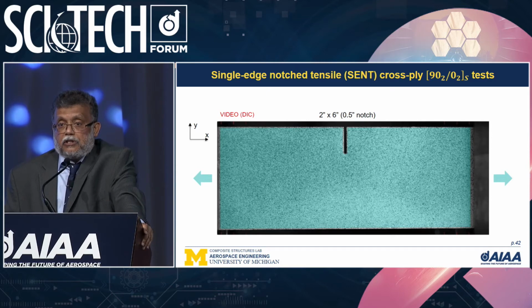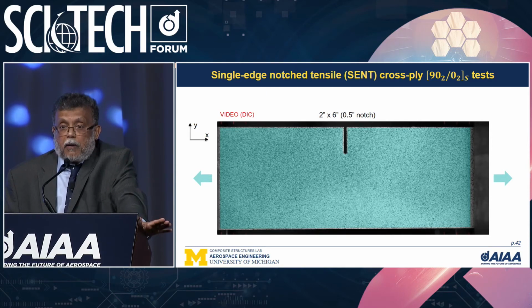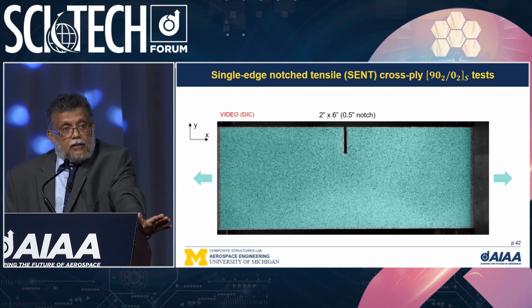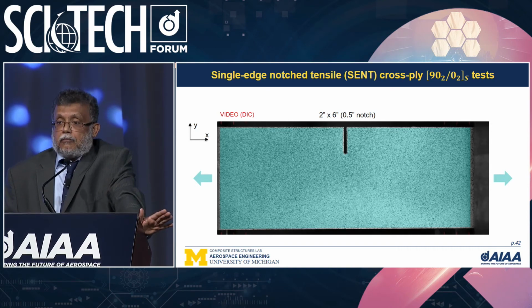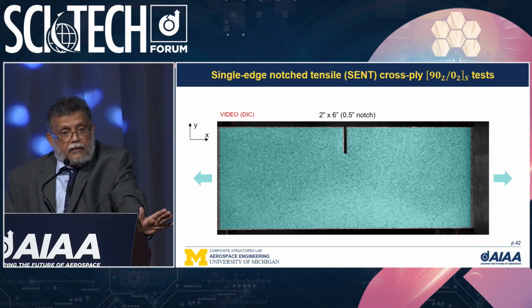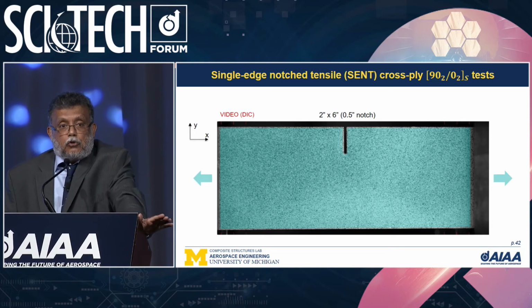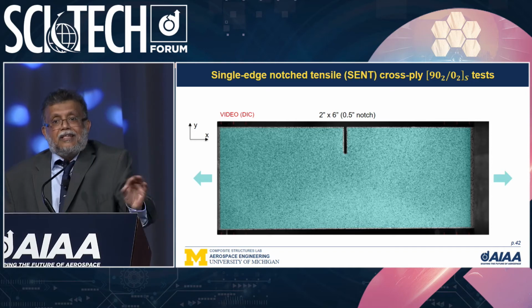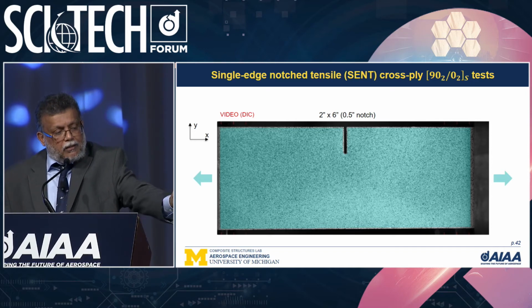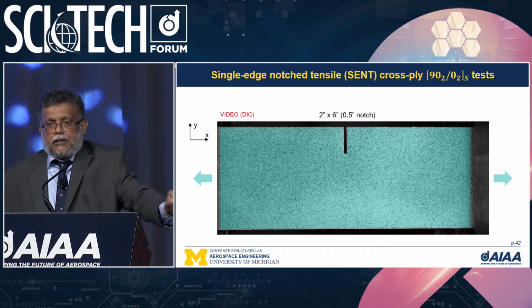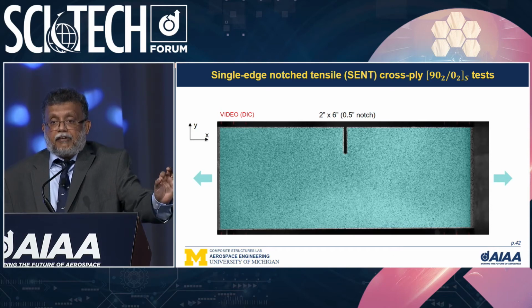Finally, I want to show you a single edge notch tension test. This is for a cross ply. This is a validation test, not to mean that people are going to use cross plies in airplanes. This is done to show that the model we've developed is able to capture the interactions between the notch and the layers of the laminate very accurately.